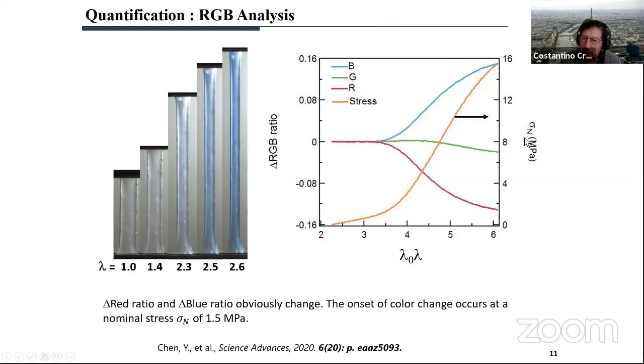Here we show you the nominal stress because we see that really it's a force per molecule. And the onset of color change here happens around 1.5 megapascal. Above that, we have a continuous color change. And this continuous color change is not because the molecule changes its color, but because the number of molecules that are activated increases with macroscopic stretch.